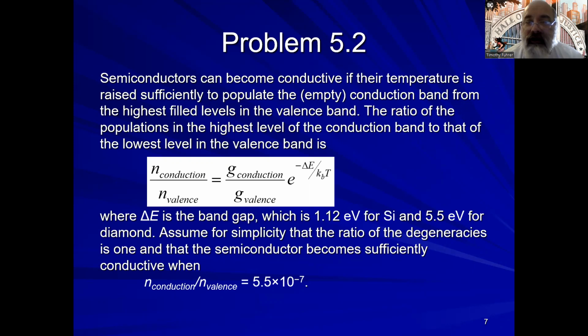It relates a little bit to the problem that we looked at with the sodium line. We said if we line up sodium atoms and treat them as particles in a box and make one long box, what will the energy difference be between the valence band and the conduction band for that string of atoms? And we got a very, very small number, and we saw that it was very easy for sodium to conduct electricity.